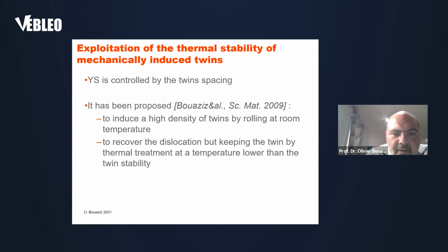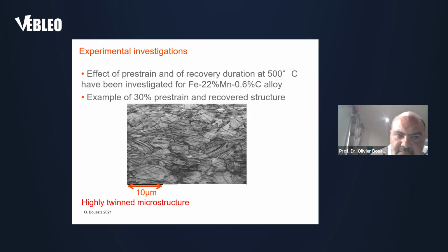So the idea is the following. We know that YS is controlled by the twin spacing. So it has been proposed to induce a high density of twins by rolling at room temperature and to recover the dislocations, while keeping the twins, by a thermal treatment at a temperature lower than the twin stability. The first results I can show you are for material deformed by rolling. You can see an example of the microstructure obtained after 30% of pre-strain and recovery treatment. You see that all the twins are kept in the structure despite the thermal treatment.